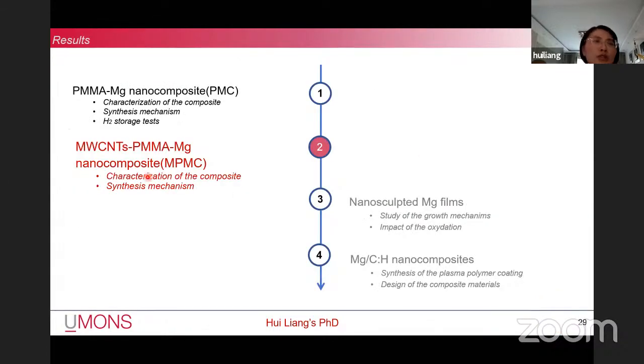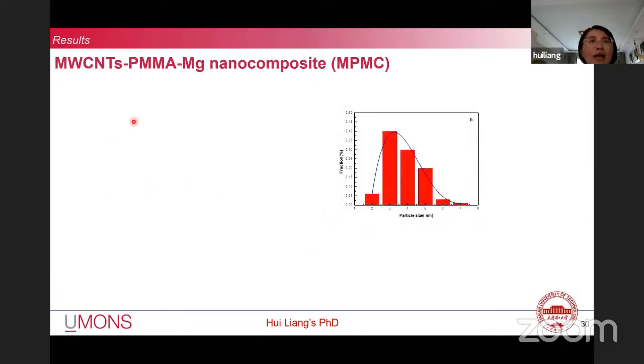In order to further reduce the size of Mg nanoparticles to improve their thermodynamic and kinetic properties, carbon nanotubes were added, producing MPMC, the composite, including the characterization of the composite and the synthesis mechanism. For the composite MPMC, refer to the distribution of Mg nanoparticles. The Mg nanoparticles have an average diameter of about 3.6 nanometers.